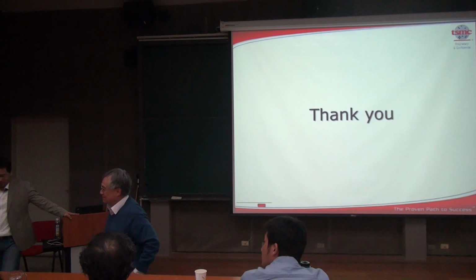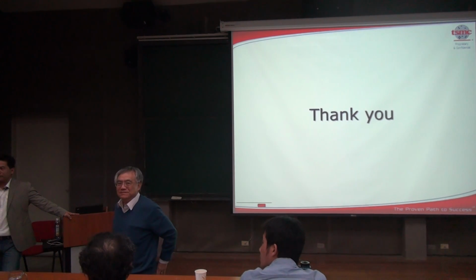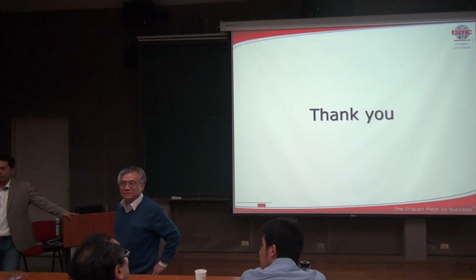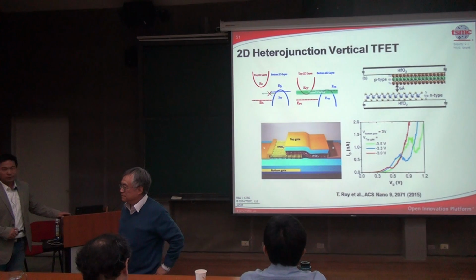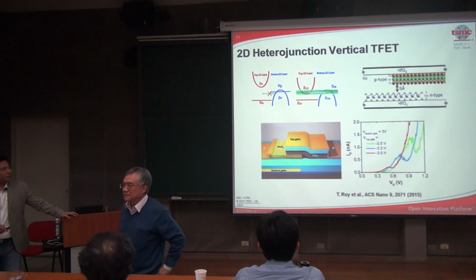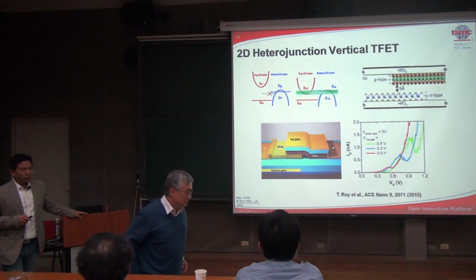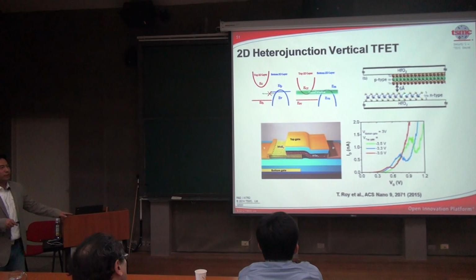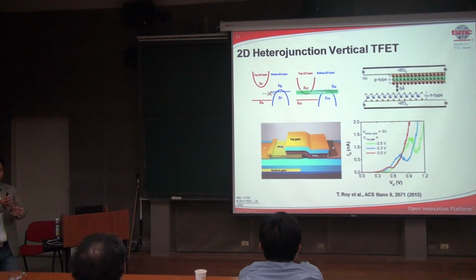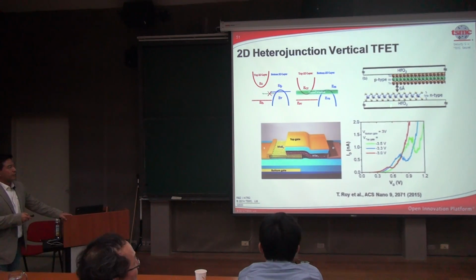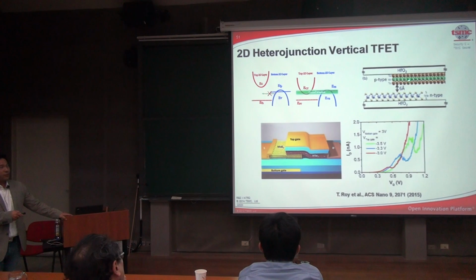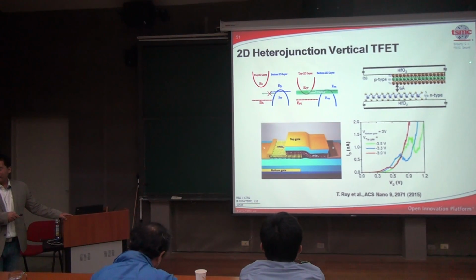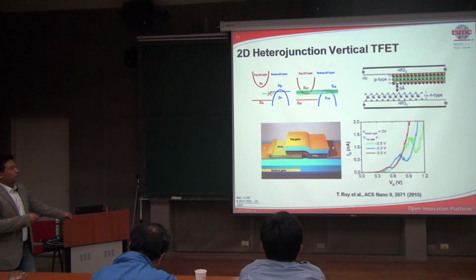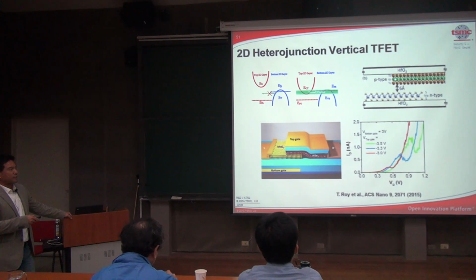Could you make a quick comment on the vertical device using the 2D material and also the planar device? I think you mentioned some tunneling activity. So is the challenge in the technology or some difference in intrinsic property? Yes, that's a very good question. Even though this looks like a planar device, you can make this in a vertical structure as well. But the idea to make this work is to control the spacing here and the clean interface of these two materials. You don't want them to have any covalent bonding, because then you will have a direct current conducting path that destroys your FET operation.